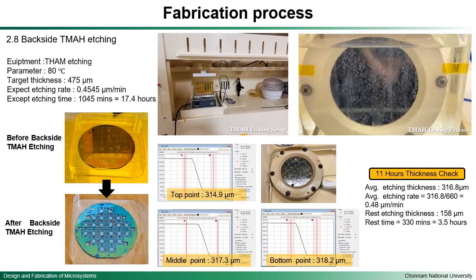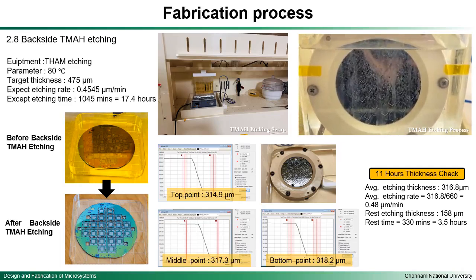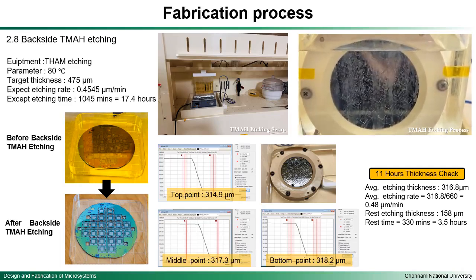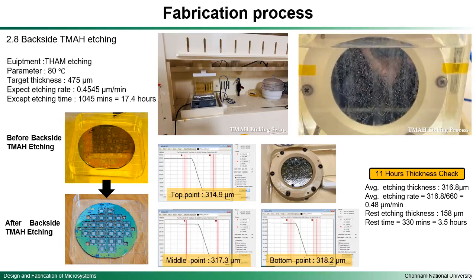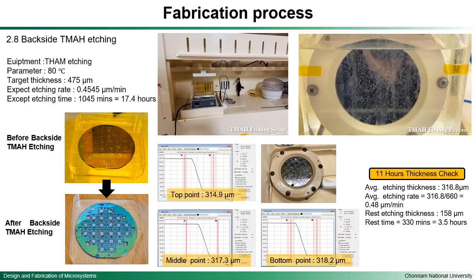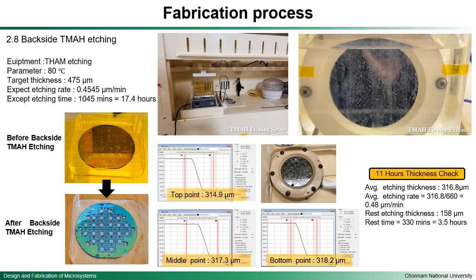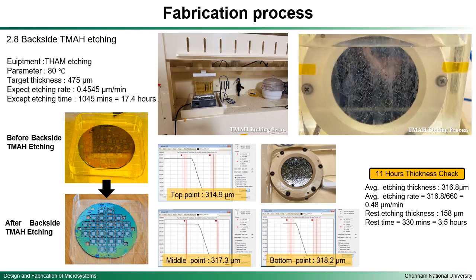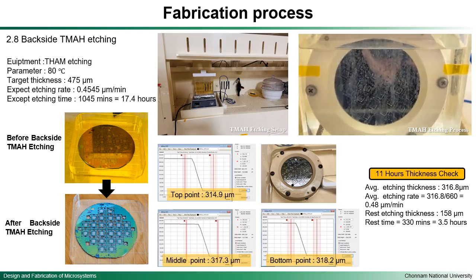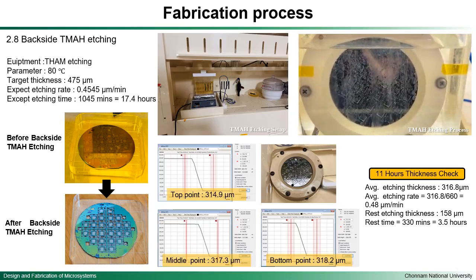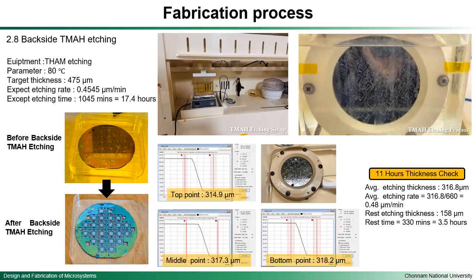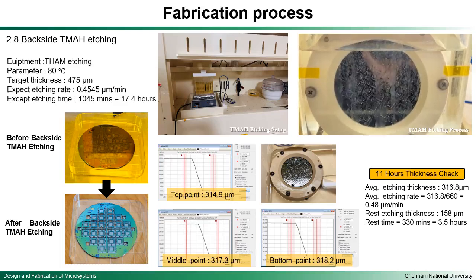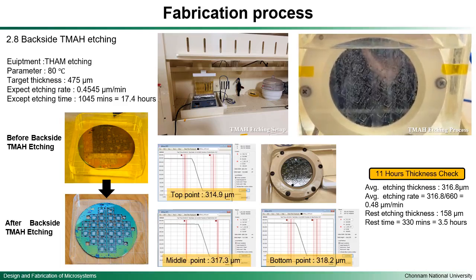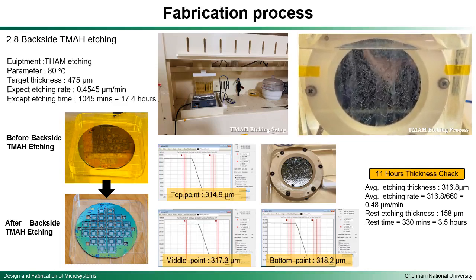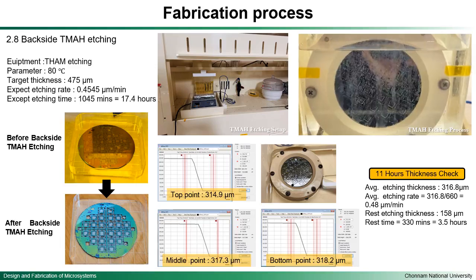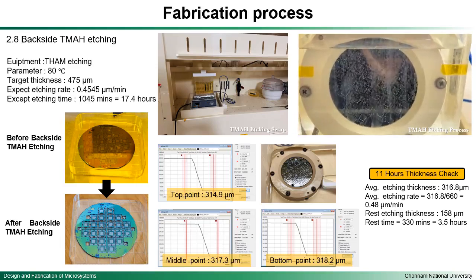The average etching thickness is around 316.8 microns. So the average etching rate is around 0.45 micron per minute. Based on the target thickness, we subtract the average etched thickness, and the remaining thickness is around 158 micron. Based on the average etching rate, we calculated the remaining time to be about 3.5 hours.